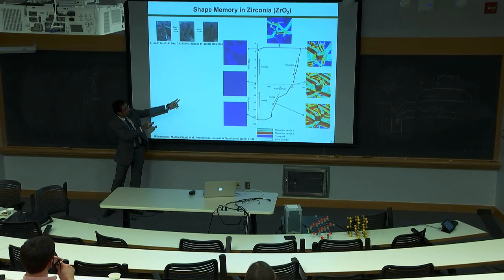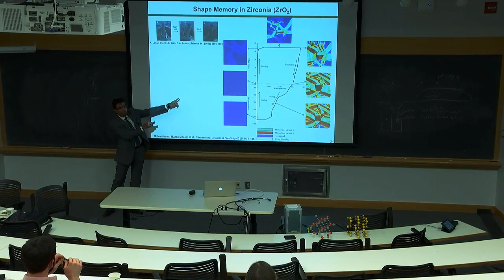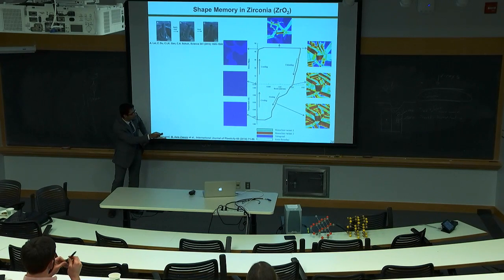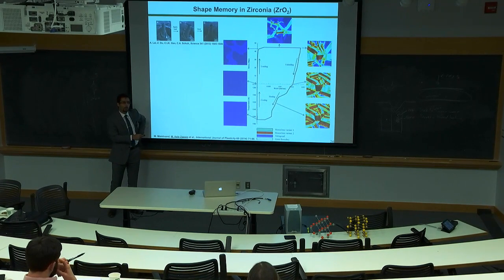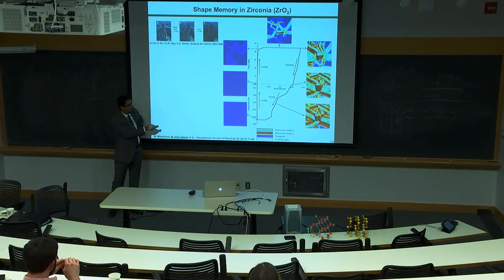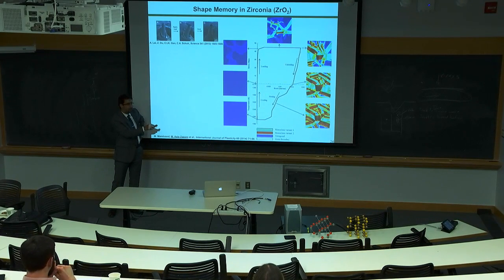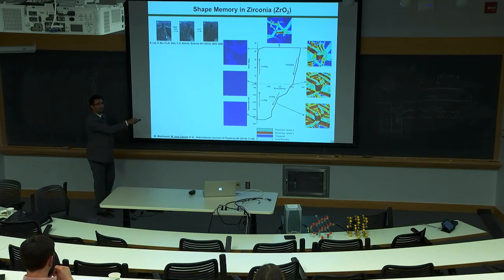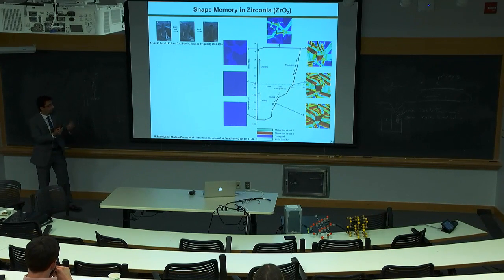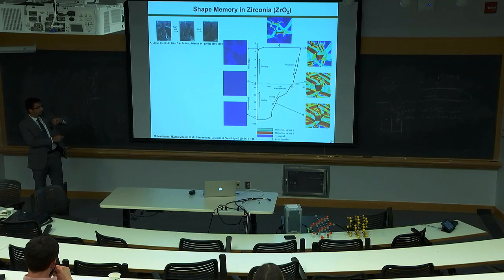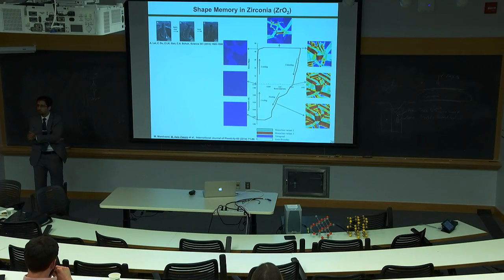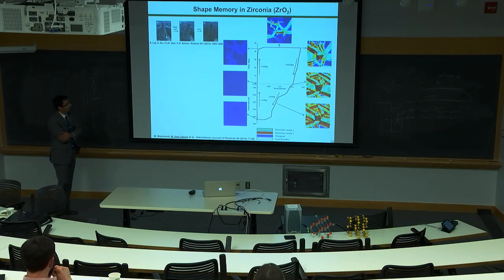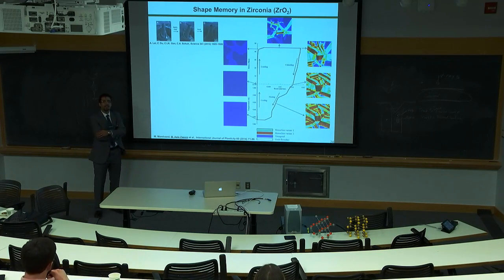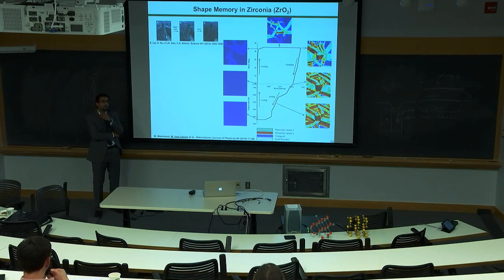We apply loading, go to transformation, plasticity, unloading. Here, we get transformed twin phases. But it's not going to go back to the initial shape by itself; you need to heat it and cool it, and you can get the initial microstructure phase. So basically, you can predict, but again, what are the limitations of this model? The limitation is this model cannot see the defects, dislocations, deformation mechanism, or failure mechanism.